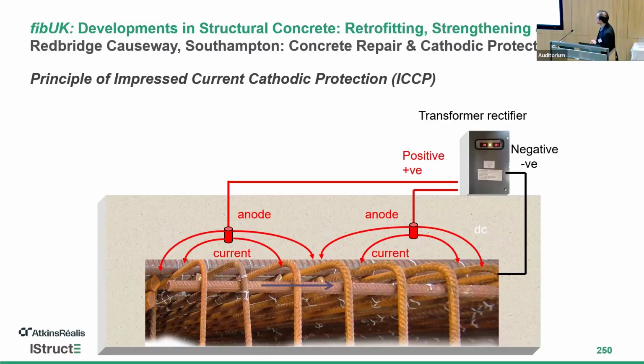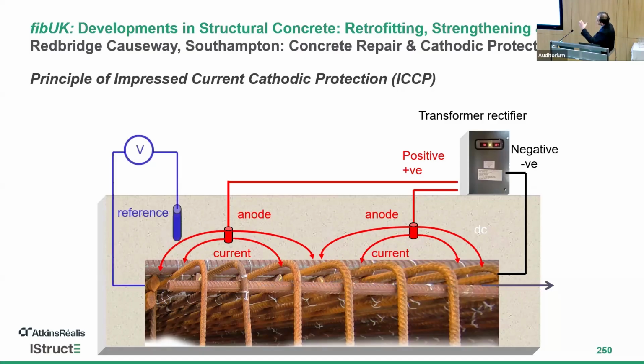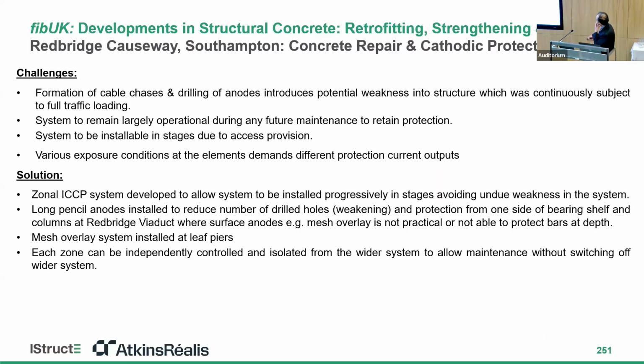Hence, steel corrosion will be stopped or minimized, and the rate of corrosion will be reduced quite significantly over time. And in order to prove that the system is working and protection is provided, we are monitoring the CP system using a number of probes like reference electrodes or decay probes, to maintain and monitor the system over time. So for Redbridge Viaduct, and any CP system installation, there are a number of challenges.